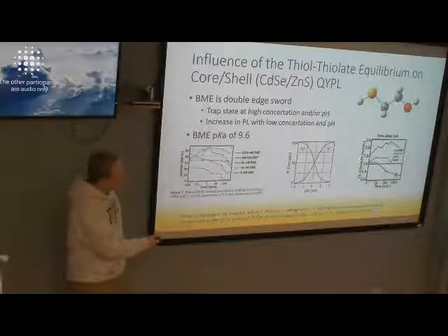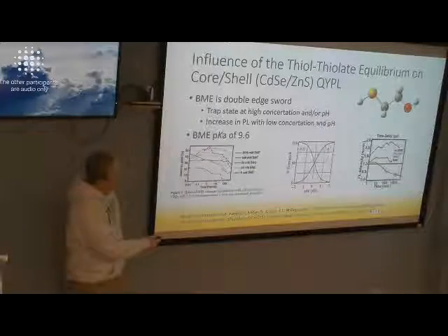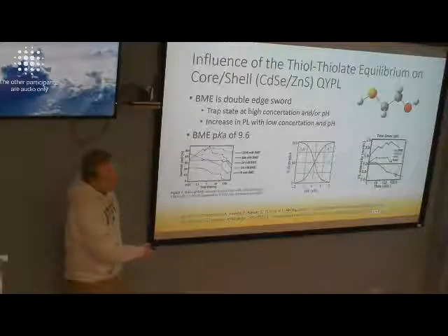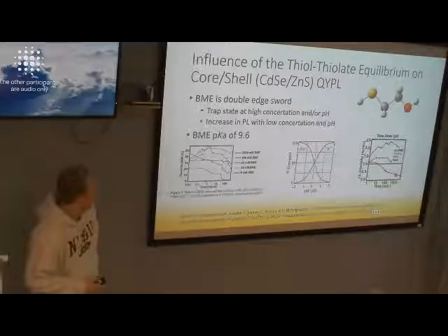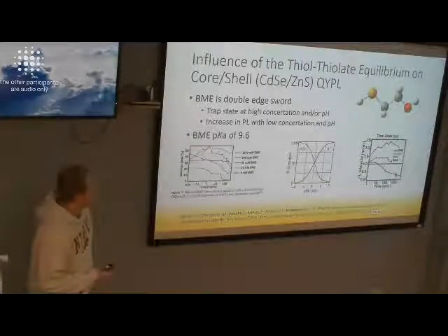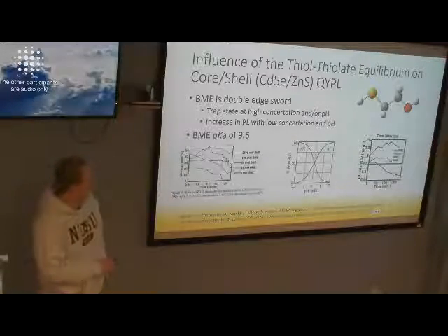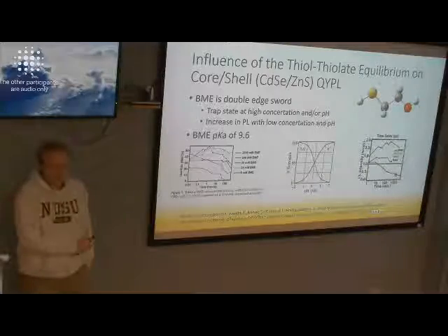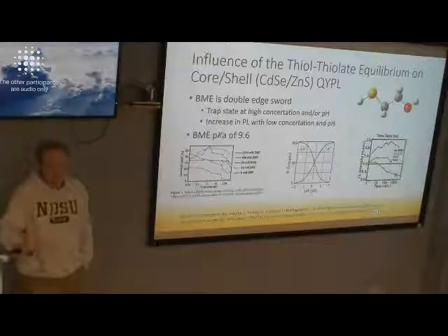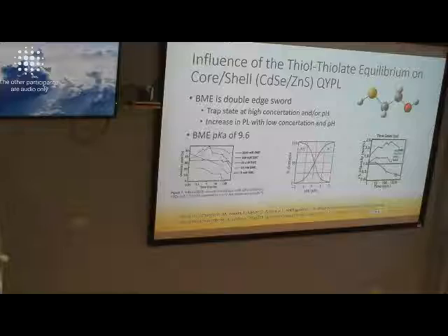So this has more of this compound, the thiol. The blue line corresponds to the red line on the middle graph. So from here we see that thiol, not thiolate (thiolate is the deprotonated form), is important for having highly emissive quantum dots.